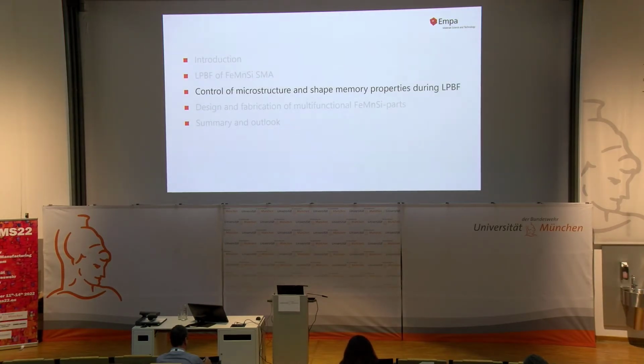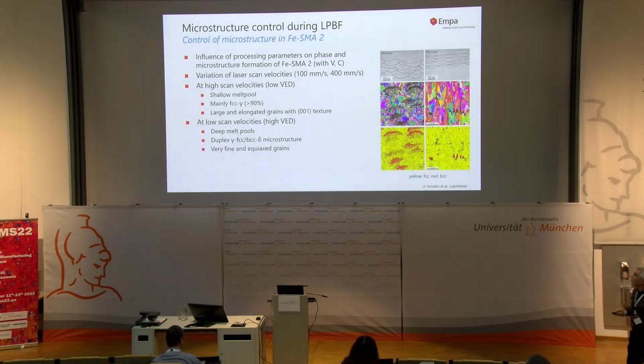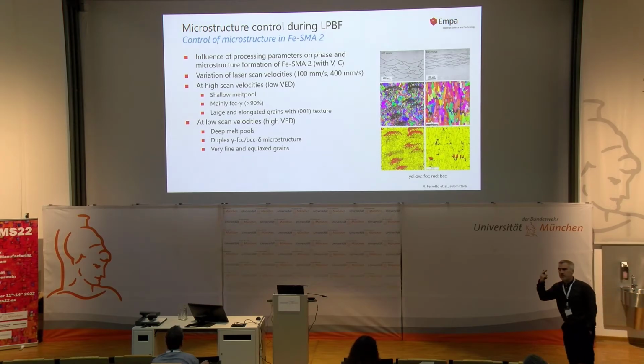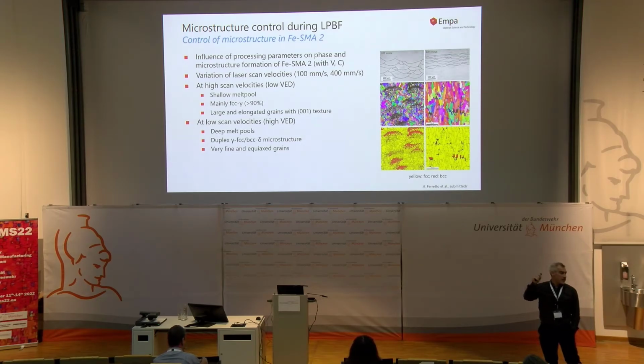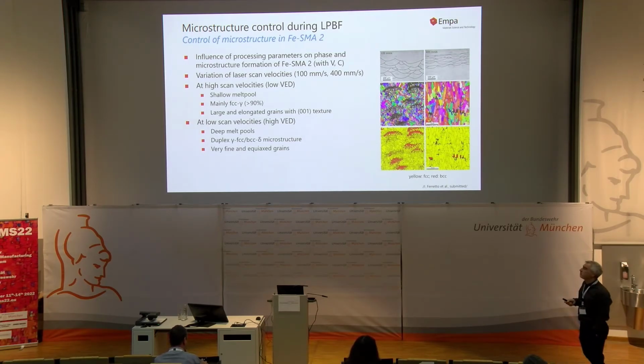Okay, now is that good for something? Remember, we have a lot of BCC delta in our material, which in steels is usually considered to be detrimental for the mechanical properties. But we asked ourselves, could that be good for something? And maybe some of you remember our paper from, I think, 2018, where we played a bit with these high nitrogen steels, so selective evaporation of nitrogen and playing with phases in nitrogen. We had something similar in mind here.